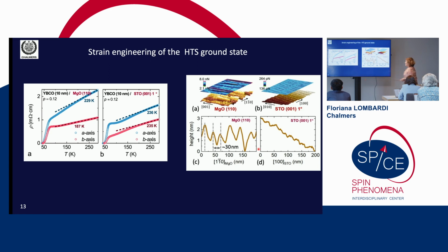Then, well, what is so peculiar in these films? What did we do to the films to get such high anisotropy? Before growing the films, the substrates were reconstructed. So we had annealing at high temperature so that the film deposited on top would be untwinned.